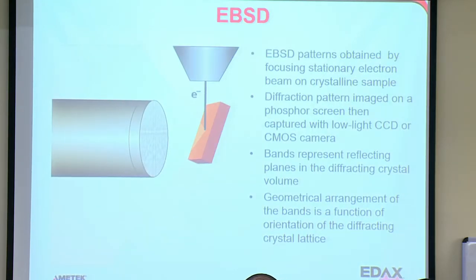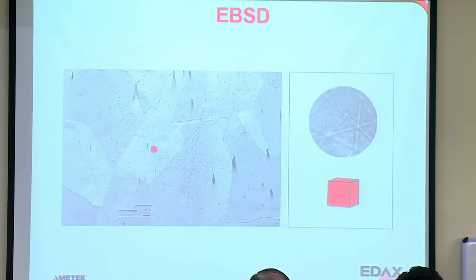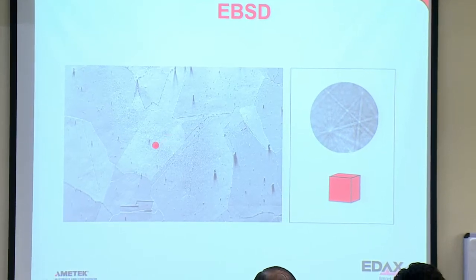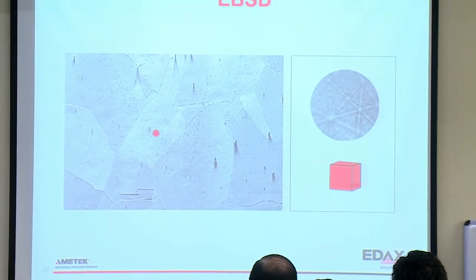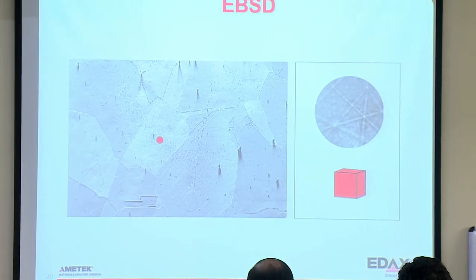So let's get back to EBSD. The key here is we have a stationary electron beam. As it interacts with the sample, it produces diffraction, and we can capture that with, like I said, a phosphor screen here. Behind the phosphor screen are lenses and a camera to detect the patterns. And it's the geometrical arrangement of the bands that we're interested in, because that tells us the orientation of the crystal lattice in the diffraction volume. So as an example, I put my beam on my sample here on this grain, I get this pattern, and I get that pattern because the crystal is oriented this way.